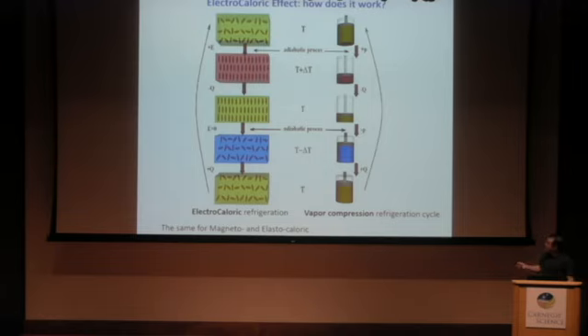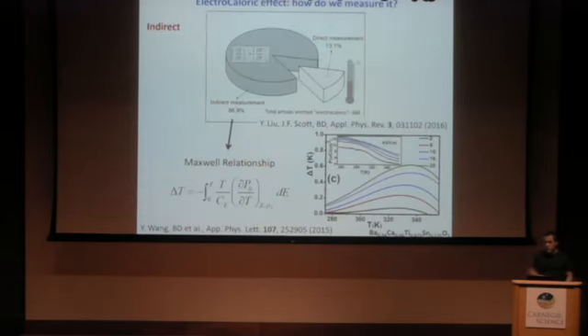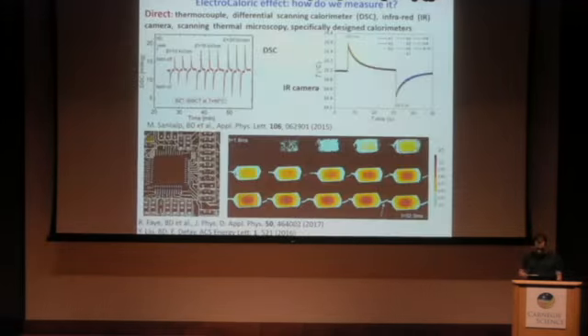And this can be applied for magnetocaloric, elastocaloric systems. So how do we measure this? Actually, most of the time, people use these so-called Maxwell relationships, and the idea is just to measure the polarization as a function of temperature, and then you take the derivative of the polarization with respect to the temperature, and then you calculate the change of temperature. It works rather well, actually, but keep in mind that the value that you will have is an estimation. So it's better to use this technique for trends, essentially. And there are also some direct techniques, and some of them are described here.